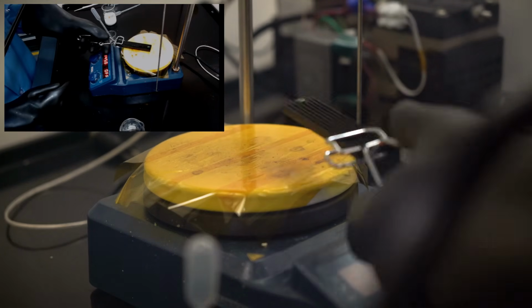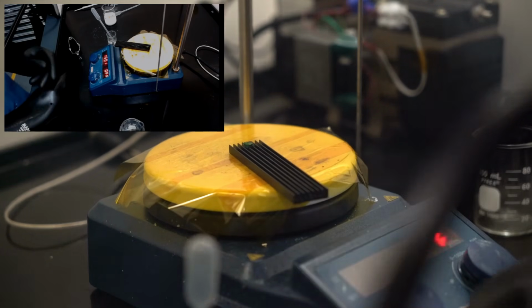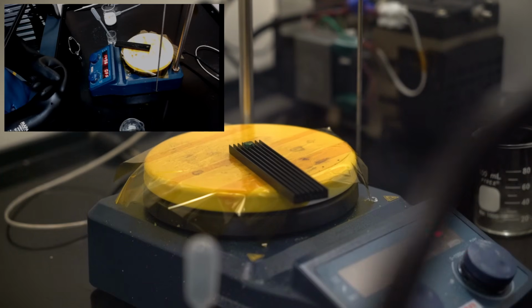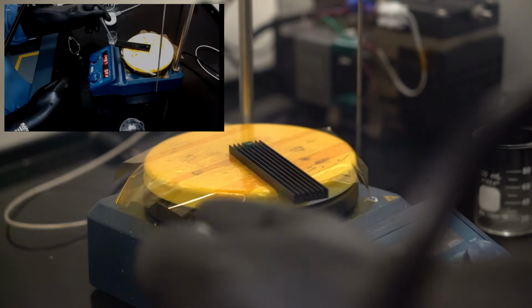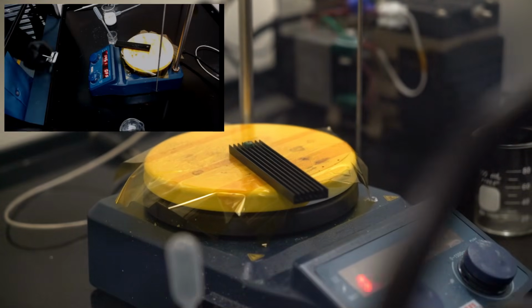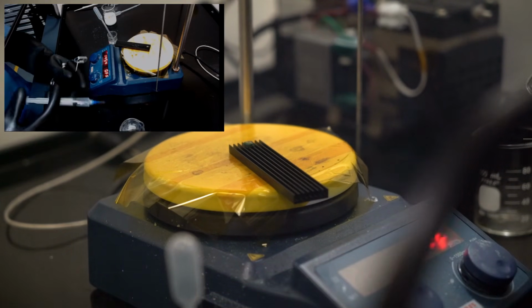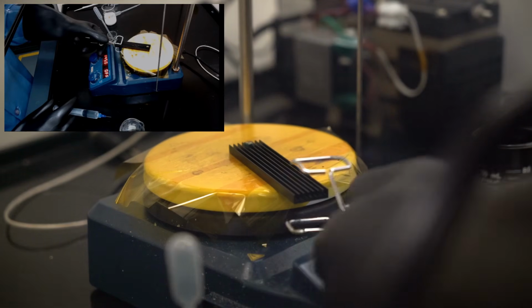since you aren't usually controlling the temperature of the sample directly. It's too small to get any kind of a thermocouple or anything on. Typically, you're just controlling the hot plate temperature and then relying on that as a proxy for sample temperature. And so figuring out what to set the hot plate at to get your sample at the desired temperature can be a little bit of art. I usually find around 140-ish with this particular hot plate, and this particular sample holder works decently, but...